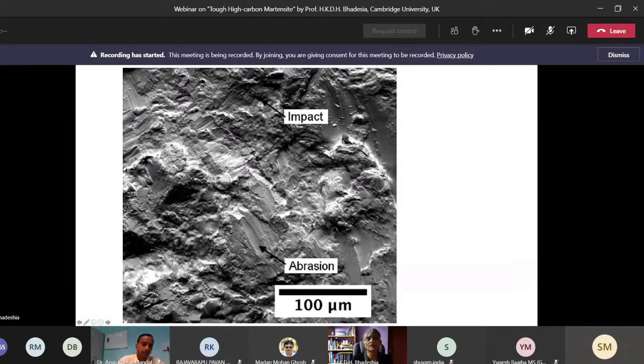And if you look at the surface of that after the impact tumbler test, you can see very clearly these are regions of abrasion where the granite particle has basically cut the steel. And these are regions of impact where we even embed granite particles inside the material. You wouldn't be able to embed the particles if this was a brittle material.